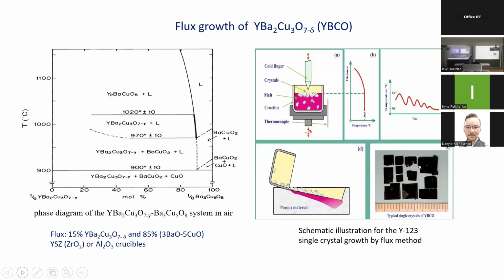Now the results for the flux growth of YBCO crystals, the system that is the most well studied. So we know practically everything about this system, and we know the flux composition. We know the temperature range, we know the corresponding phase diagram. The main difficulty is that the material solubility in this flux is very low. So we have to apply very low cooling rates, half a degree per hour, maximum 1 degree per hour.